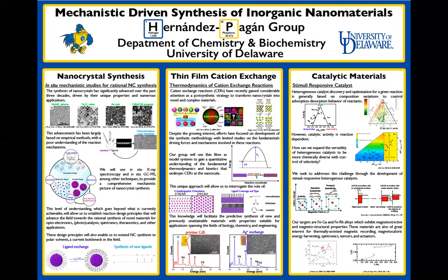And so you can see here, for example, in this plot where we have the binding of a hydrogen to different metals. You can see that at the top of this triangle on the right column, platinum is the best because it has in-between binding, so it doesn't bind protons too strong or too weak, and that's the reason why platinum is known as one of the best catalysts for making hydrogen.